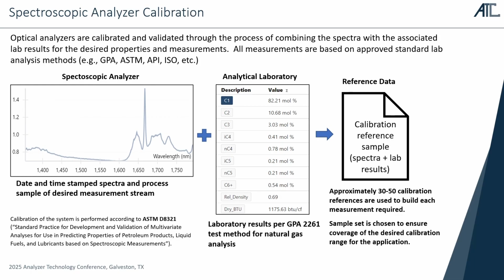We can combine those together and generate a chemometric calibration model that predicts what the composition or property of interest is in that sample. And ASTM D8321 says that we need 30 to 50 calibration references to build a robust measurement model. We want to make sure that those 30 to 50 samples are chosen across the full range of variation of the process. So if you've got a crude oil sample and the vapor pressure in that process happens to range from 6 psi to 12 psi, you want to make sure you get those extremes, and some samples in the middle, so you're measuring the full variation of the process.